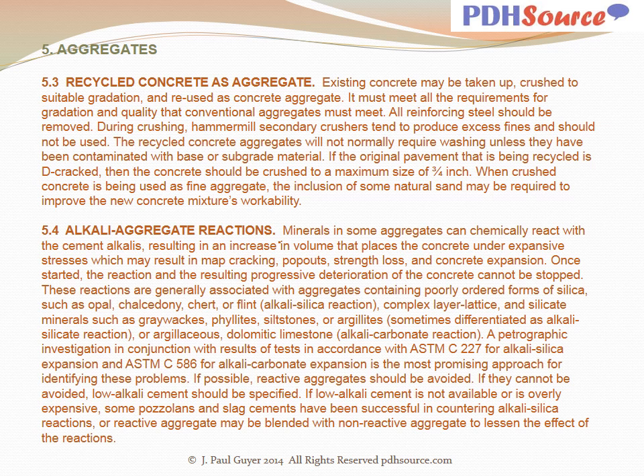Minerals in some aggregates can chemically react with the cement alkalis, resulting in an increase in volume that places the concrete under expansive stresses, which may result in map cracking, pop-outs, strength loss, and concrete expansion. Once started, the reaction and the resulting progressive deterioration of the concrete cannot be stopped. These reactions are generally associated with aggregates containing poorly ordered forms of silica such as opal, chalcedony, chert, or flint, alkali silica reactions.